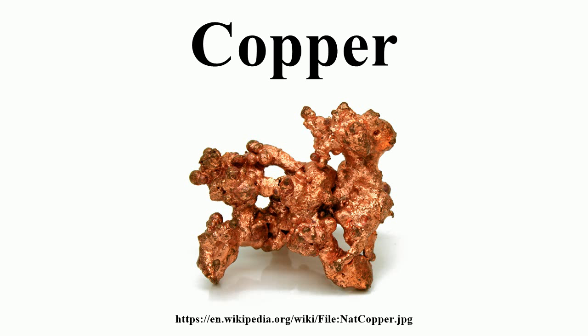It was then electrolytically refined and the anode mud exploited for the platinum and gold it contained. This step exploits the relatively easy reduction of copper oxides to copper metal. Natural gas is blown across the blister to remove most of the remaining oxygen and electro-refining is performed on the resulting material to produce pure copper. Cu2+ + 2e- → Cu.